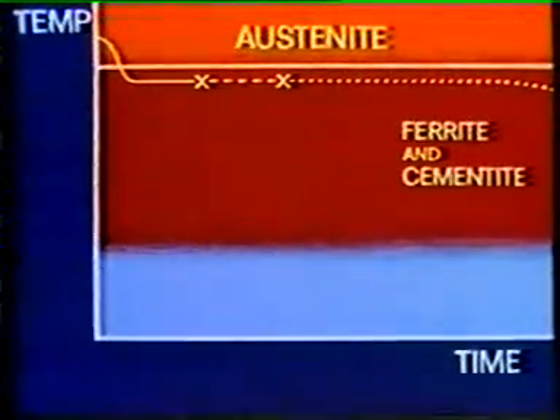The sample, in this case a plain carbon steel, is quenched in a hot lead bath, only as far as, say, 680 degrees centigrade, and is then held at that temperature. After a period of time, the austenite begins to transform into ferrite and cementite. After a further period, the transformation is complete, and the steel will not harden when it cools. The same sample of steel is reheated, and again it is quenched, this time to a slightly lower temperature. And again we plot the times at which transformation begins and ends.